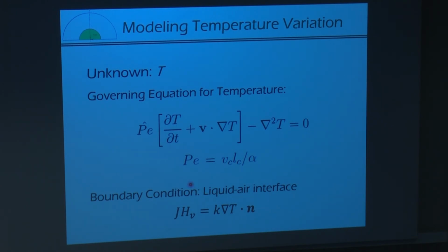So we put in the energy balance equation for a non-isothermal system. And in this case, we have the thermal Péclet number, and then the boundary condition is shown here for the heat flux that's due to the evaporation at the surface of the liquid.